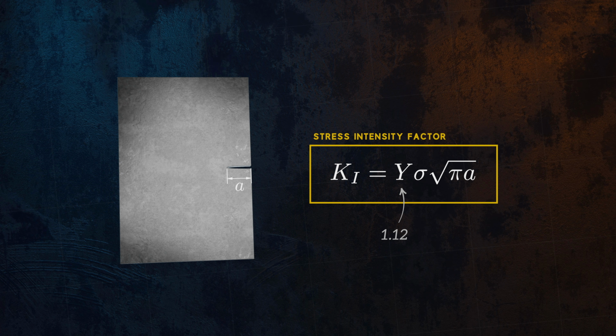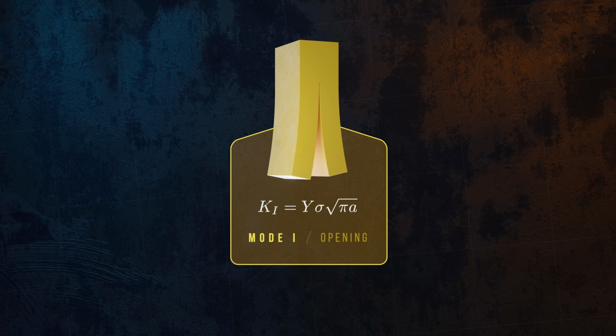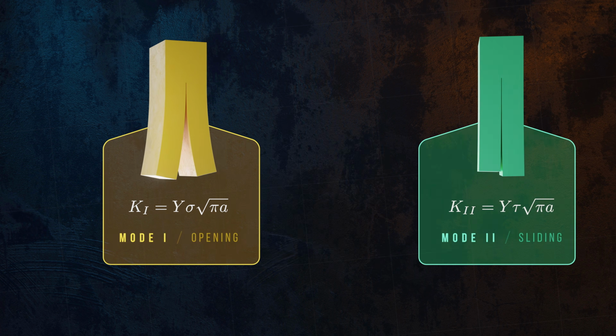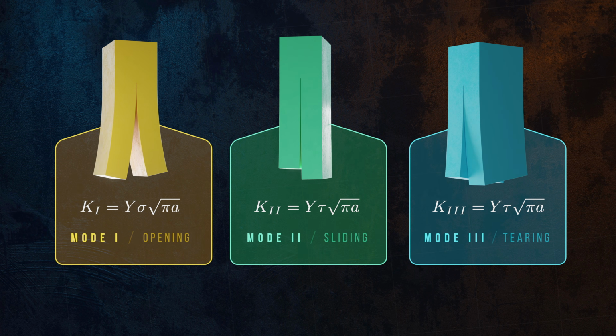The stress intensity factor is called K1 because it corresponds to the first of three fracture modes, ways in which a crack can be loaded. This mode, corresponding to opening of the crack, is the one engineers encounter by far the most often in real structures. The sliding and tearing modes use similar equations, but with shear stress instead of normal stress.